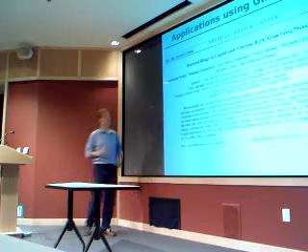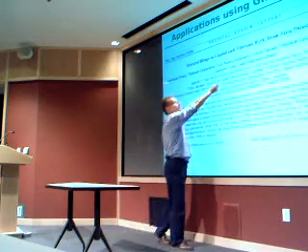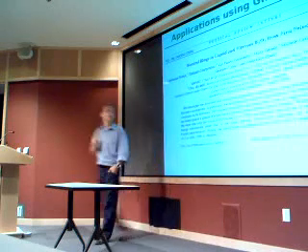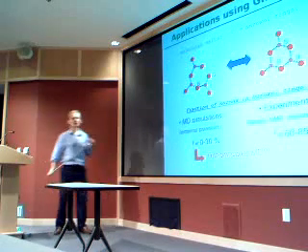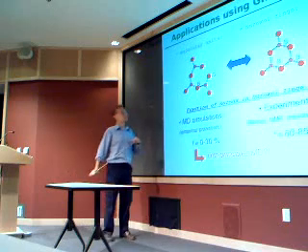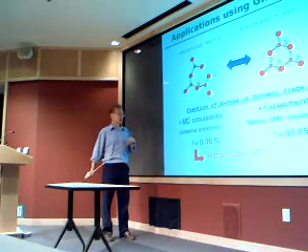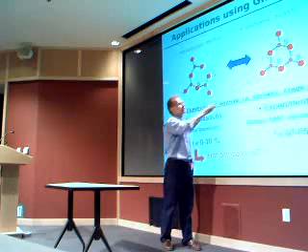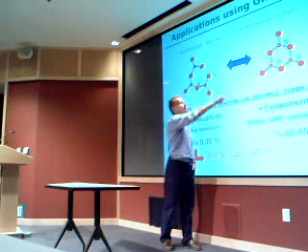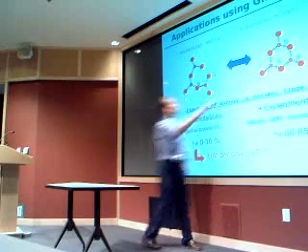Then I will maybe quickly go through one more application. I was myself participating in this, so I can tell you some more details if you want to know. This is a calculation for a glass called boron oxide, B2O3, and there was an interesting physical problem behind that. There was a controversy in the literature. What is the fraction, which is called f, of so-called boroxol rings? So these are boron atoms, these are oxygen atoms, and you always have this structural unit, and then here you have those triangles which share a corner. So that's a so-called boroxol ring.